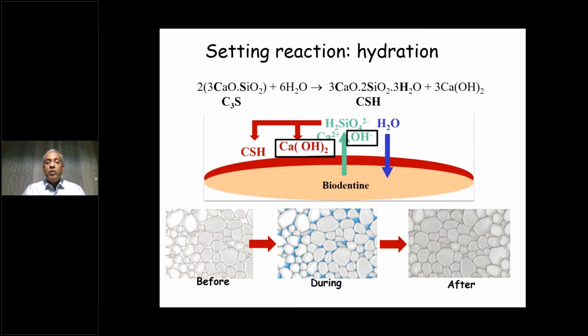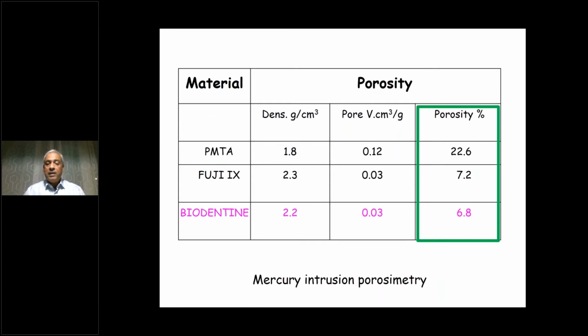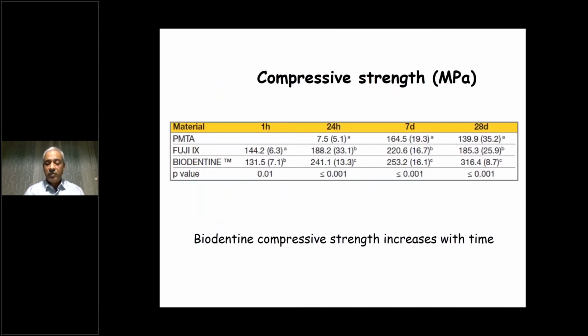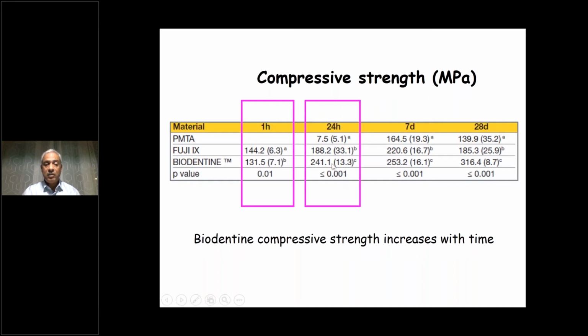Now, if you look at the porosity of Biodentine, as a percentage, you see that it's very low. It's comparable to Fuji IX, which means that you have a material which is not porous. And if it is not porous, that means it has good mechanical properties. And indeed, when you look at the compressive strength of this material, you see that by 1 hour, it is similar to Fuji IX. And the compressive strength of the material increases with time. So when you look at it after 24 hours, it exceeds that of Fuji IX. And when you look at it at 28 days, it is similar to the natural dentin.